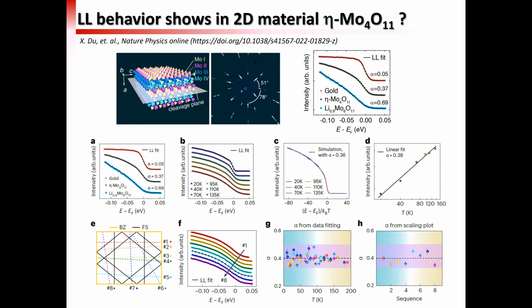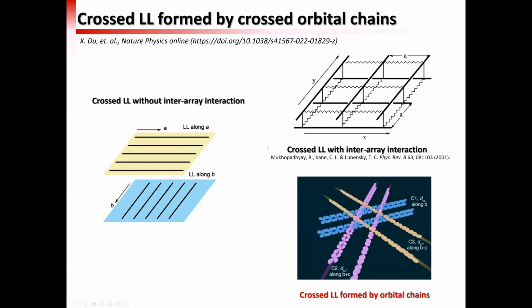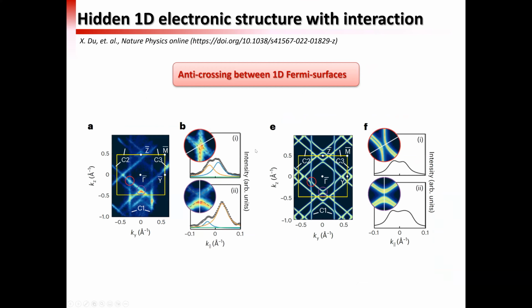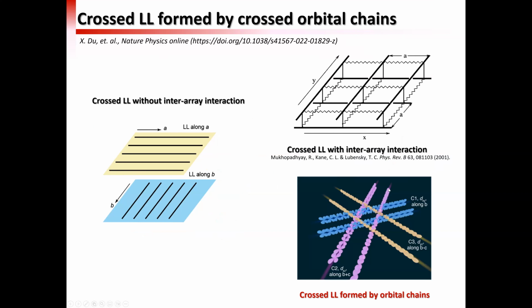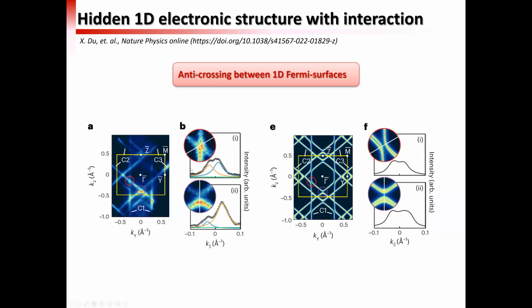So the reason those orbitals are responsible for the crossed Luttinger liquid behavior, is that because you checked the Fermi surface in the band structure? The band, yeah. We were quite surprised at the beginning, right? Then we checked the Fermi surface, and we understood that there should exist three different chains with different directions. There are three sets, about 60 degrees apart, but not exactly. We carried out the calculation, and the calculations show these three directions are special and more conductive, and the orbitals have more overlap just along these three directions. Therefore it forms three sets of chains, and if we analyze the angle and do the calculation, the result agrees with our measurement very well.